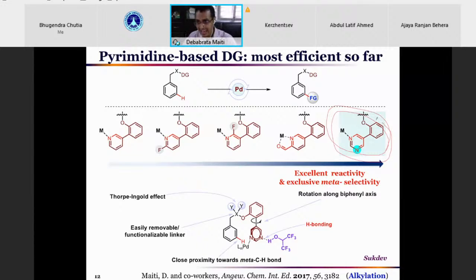And that is because this ligand can bind with the metal center more precisely than anything else for this purpose. It is a better sigma donor as well as pi acceptor, something which you see even in metal carbonyl complexes, right? This ligand-metal complex is so good that it can hold tightly on the metal center without compromising the denticity. It's a monodentate ligand. Why do we need a monodentate ligand? Because we are usually dealing with a d8 metal center in the palladium(II) oxidation state, for example. You have a square planar geometry. So if you have bidentate or tridentate ligands, the number of coordination sites is really compromised. The organic reaction that we are looking at will occupy some coordination mode as well. So it's better to keep monodenticity, okay?